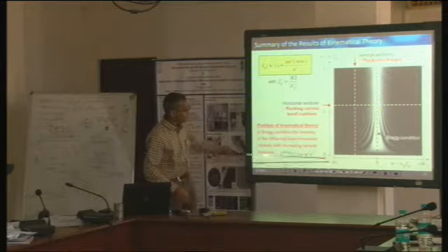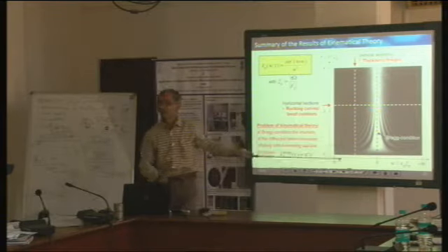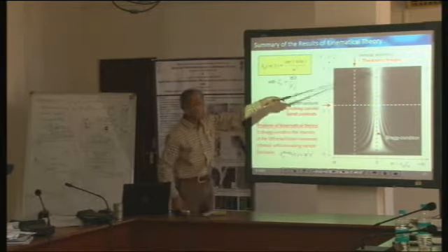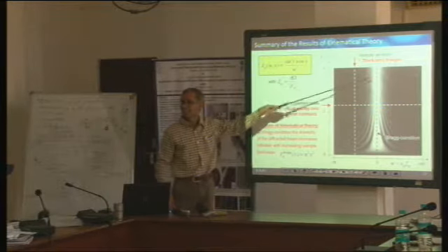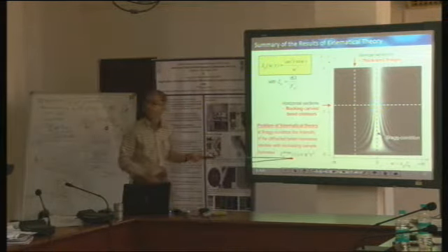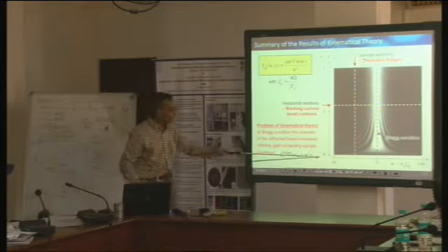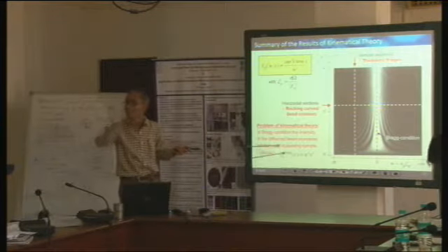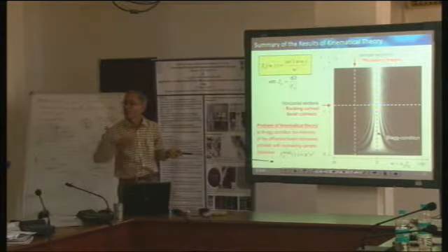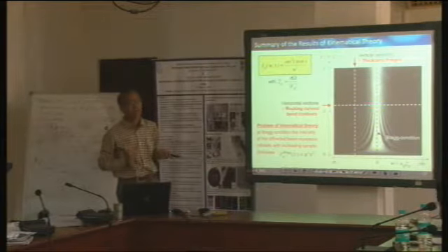Now if I increase the thickness of my sample, that's what we do when we go along this axis, what is happening to the diffracted intensity? Diffracted intensity is increasing. Yeah, and there is no end to it. It will keep on increasing. This is very artificial, isn't it?